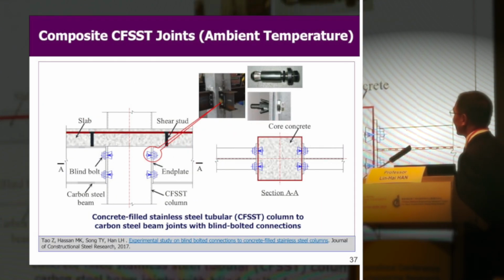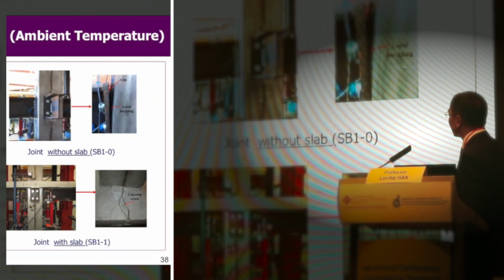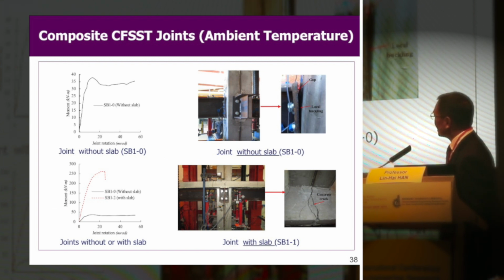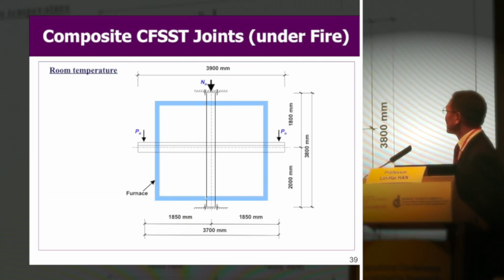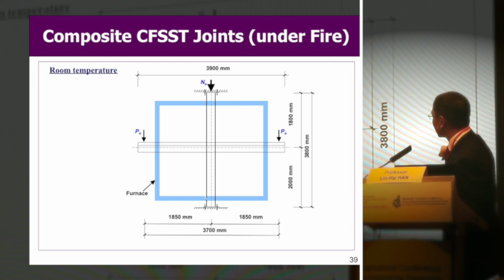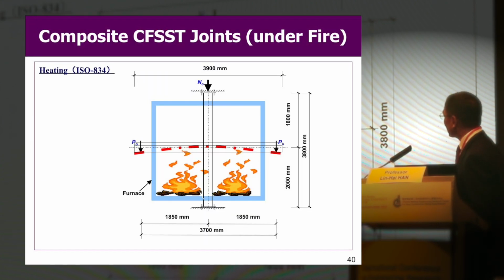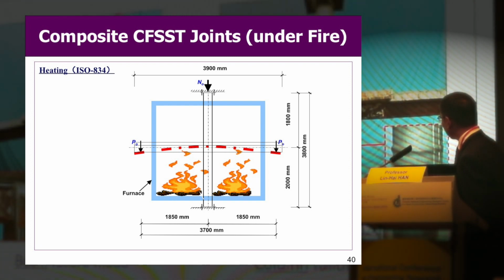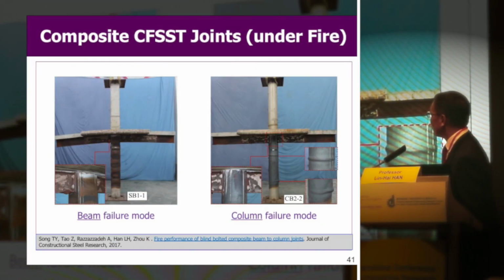So we also have done some tests of composite joints. It's a stainless steel tube filled with concrete, using blind bolts with a steel beam. You can see the moment and the joint rotation curves show a very good manner of the ductility of the structure. We also check the composite joints in fire, and also loading. This furnace actually loads on the columns and the two segments of the beam. Then fire to failure. Again, we have achieved the column failure mode and beam failure mode.